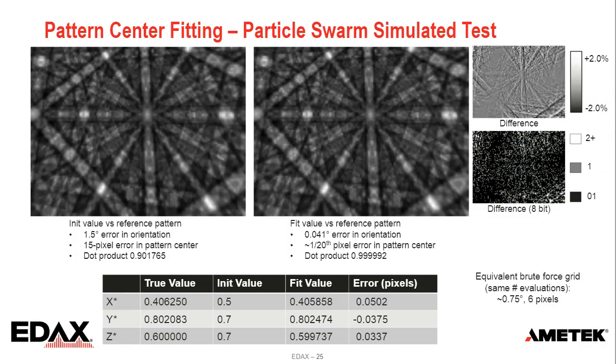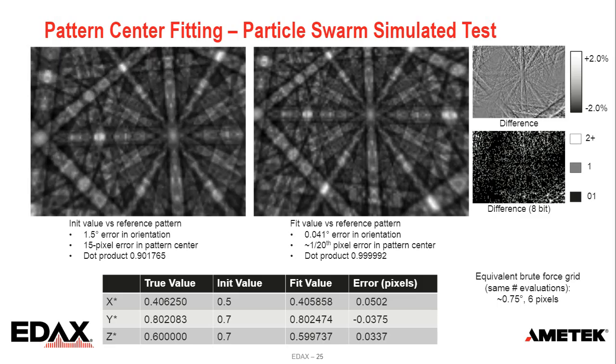And this is a big enough search window that you can just put in some default approximation, like that the pattern center is in the middle and 2/3 of the way up, and that's close enough to get you to the right answer. Compared to normal, the existing pattern center optimizations, you generally have to start off pretty close.